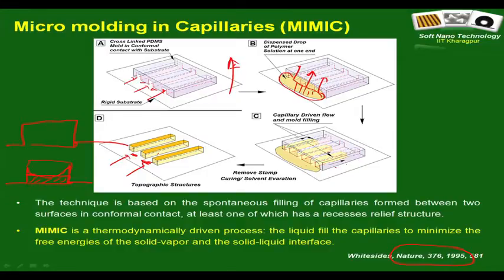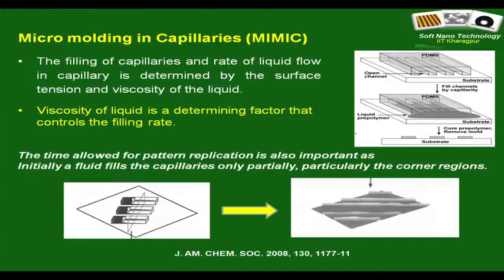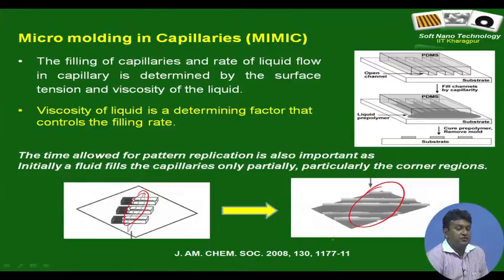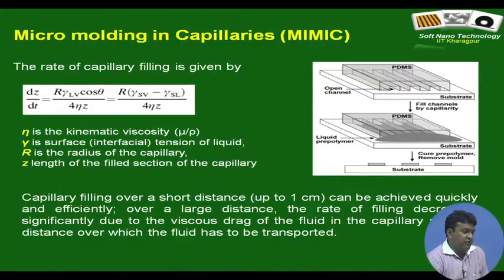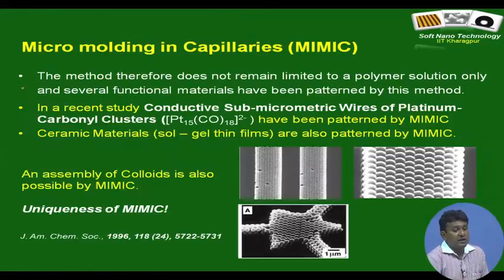The other major problem is, I will not go into the mathematical formulation, but one can get this formulation pretty easily, the capillary driving force drops away as you go deeper into the channel. So, after a certain point the velocity of mold filling becomes very small, and therefore towards the edges you often see this type of incomplete structures taking place. There are some mathematical formulations, and in fact this equation shows why the velocity drops as you go along the capillary channel.